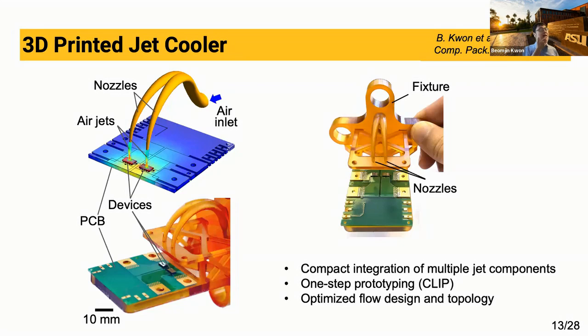And in another project, we also use 3D printing to innovate the design of jet cooler. So the jet cooling actually is a technique to create high-speed fluid flow and achieve extremely large convection heat transfer coefficient. So for example, if the flow's Reynolds number is on the order of 10,000, you can achieve the convection coefficient on the order of 10,000, which is about 100 times better than what you can achieve using slow fluid flow. Right? So because of that, jet cooling is considered as very powerful cooling approach. However, if you want to make very compact jet cooler for electronic system, it's actually very challenging if you're trying to combine off-the-shelf fluidic components.